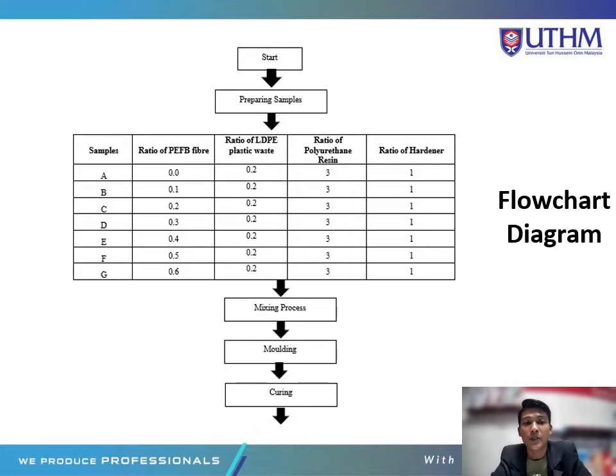The ratio of LDPE plastic waste for all 7 samples will be 0.2, equal for all 7 samples, and the ratio for polyurethane resin will be 3, also equal for all samples, and the ratio of hardener is also equal for all 7 samples. After I prepare the samples, there will be a mixing process. All the samples will be mixed properly with all the ingredients, and after that will be the molding process.